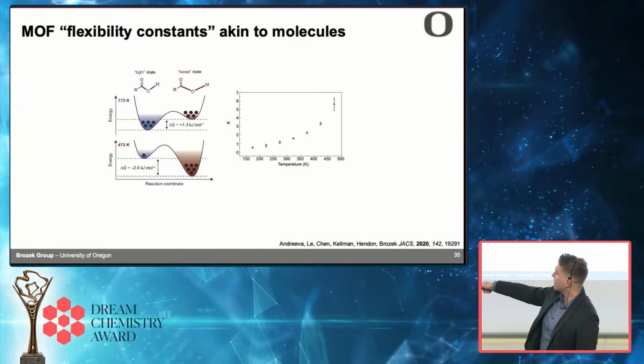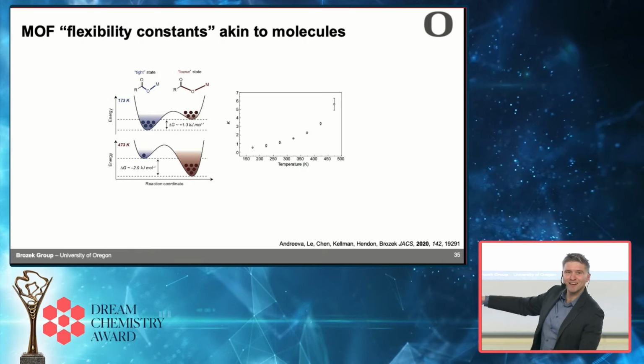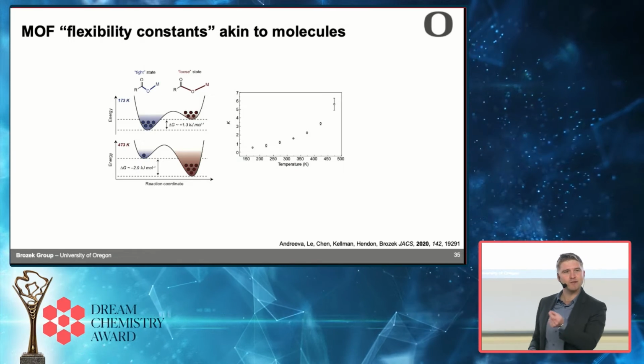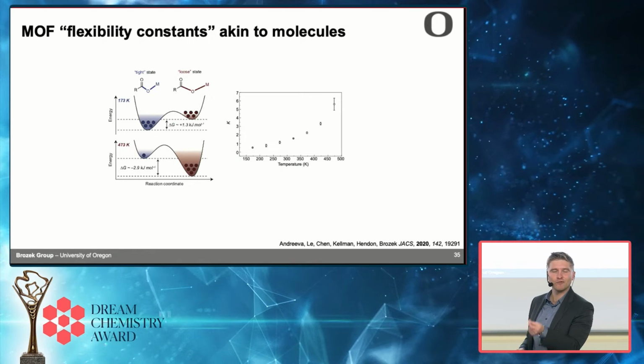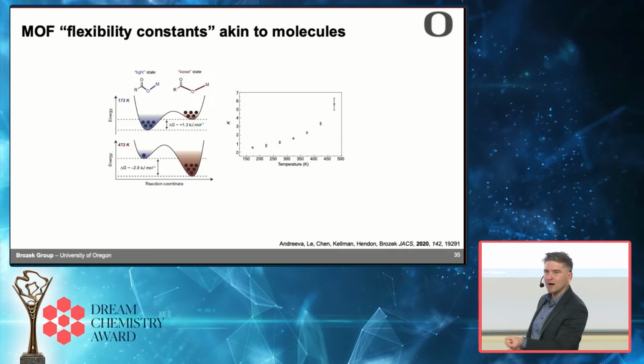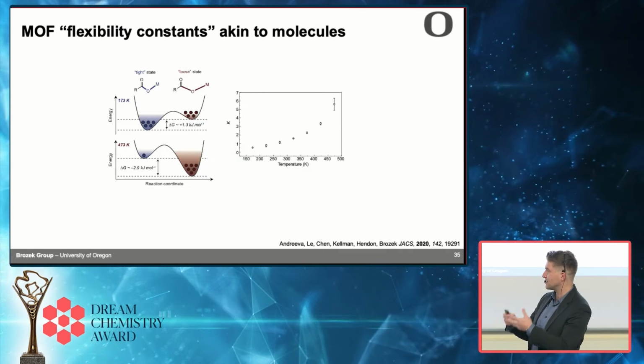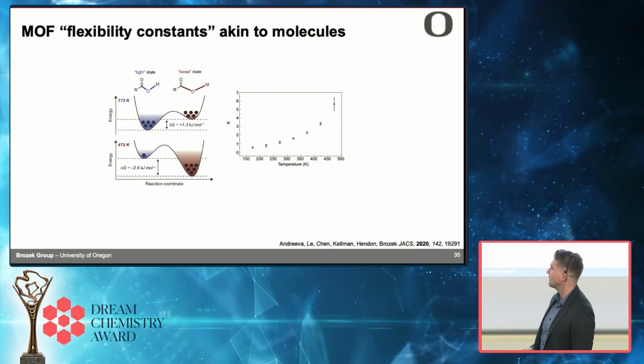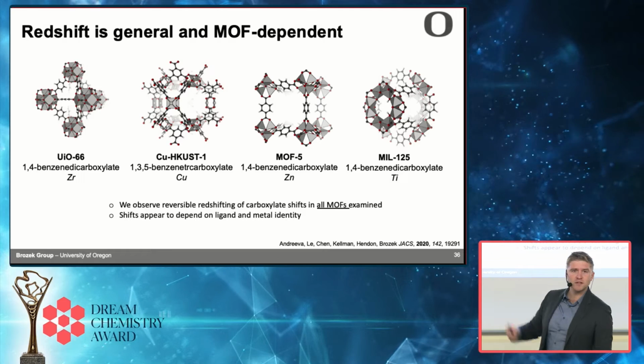Regardless of that, you can look at the value for room temperature, and if you convert that to the stability constant, it's actually remarkably similar to reported stability constants for metal carboxylate bonds, which is weird, because this is a solid state material.